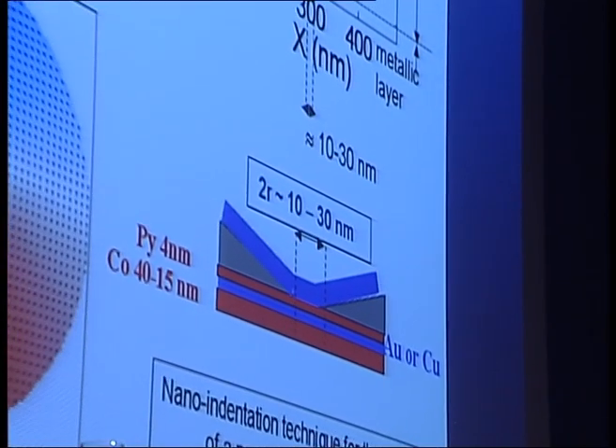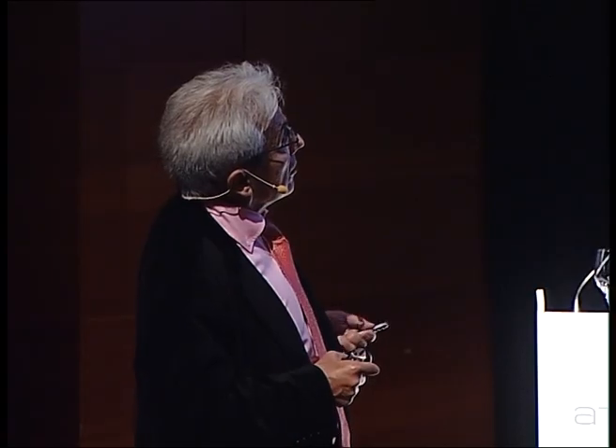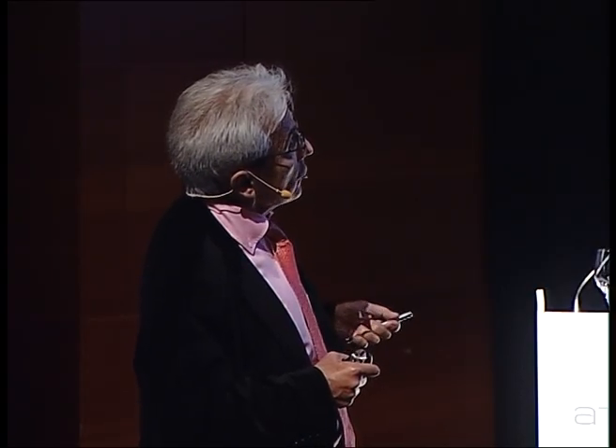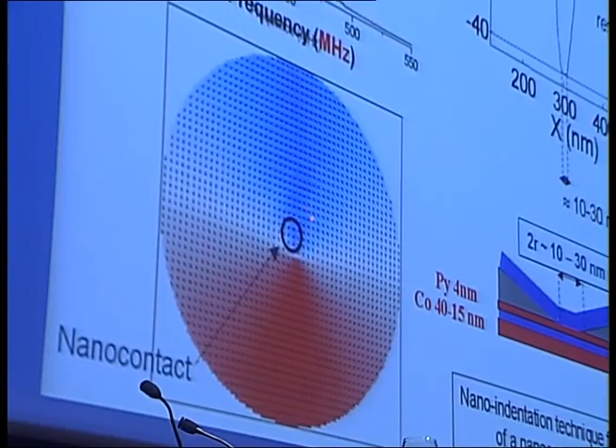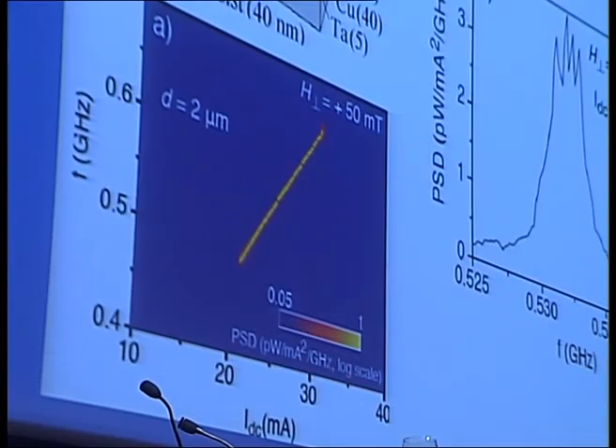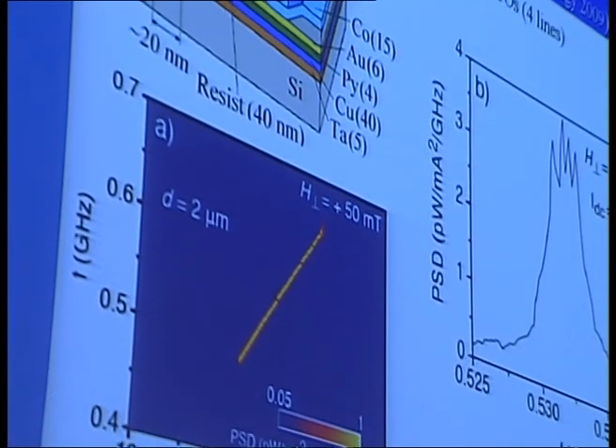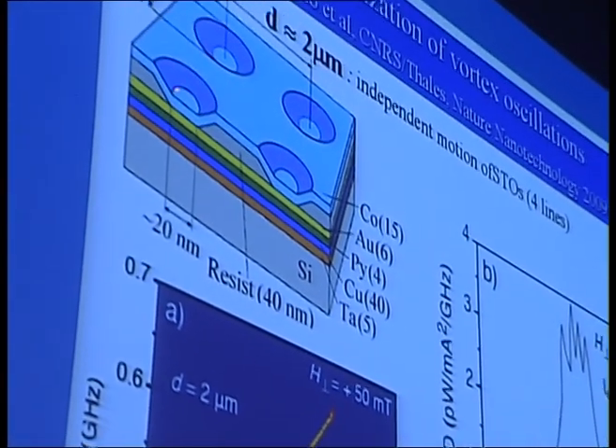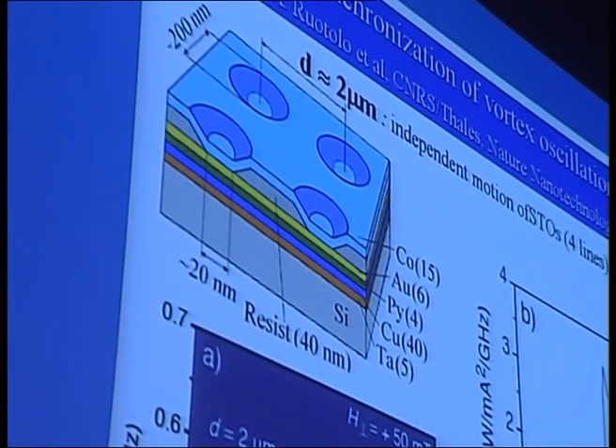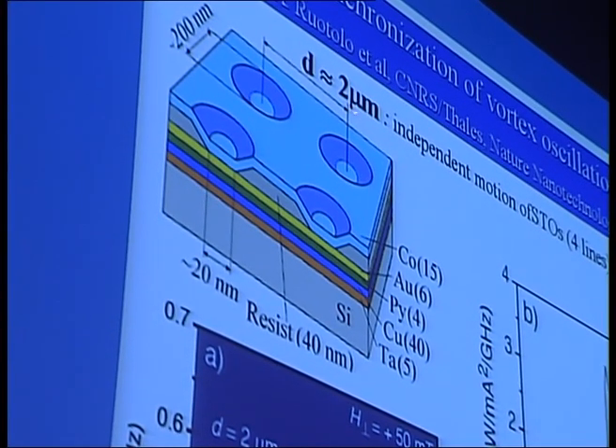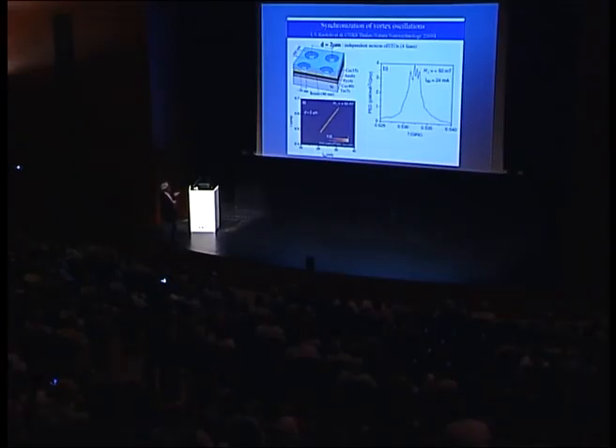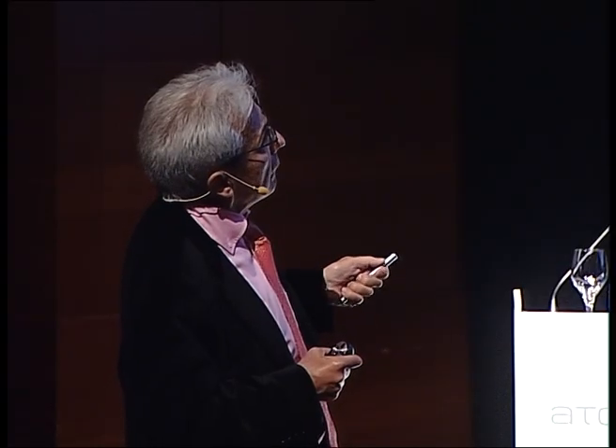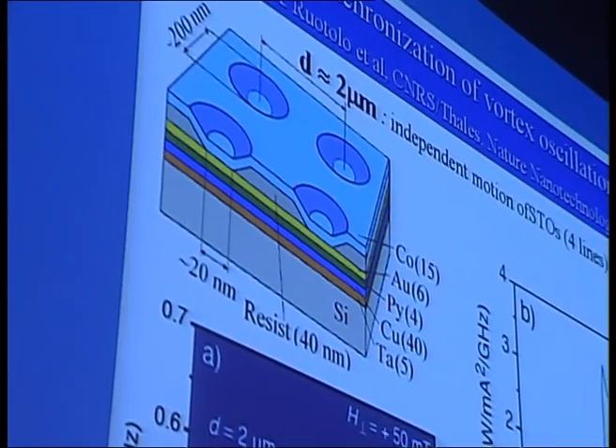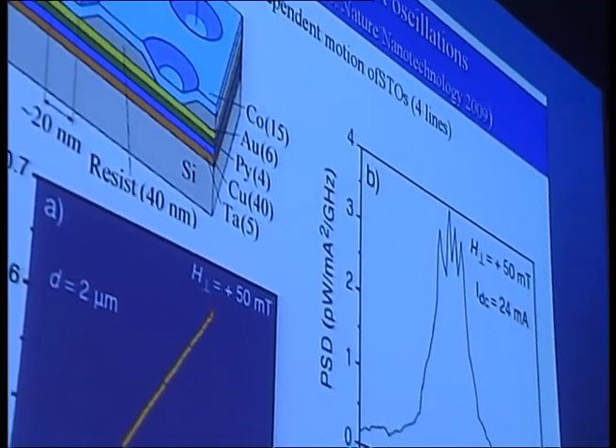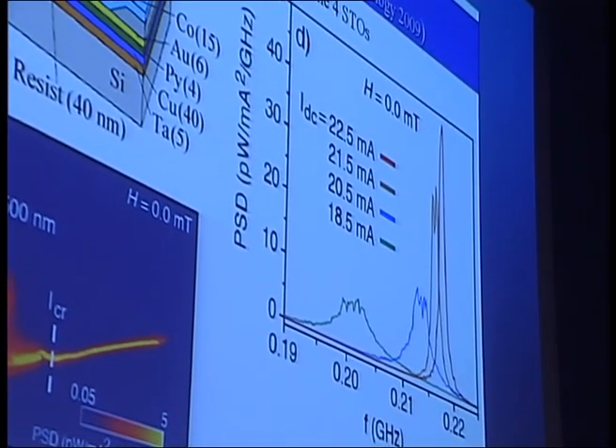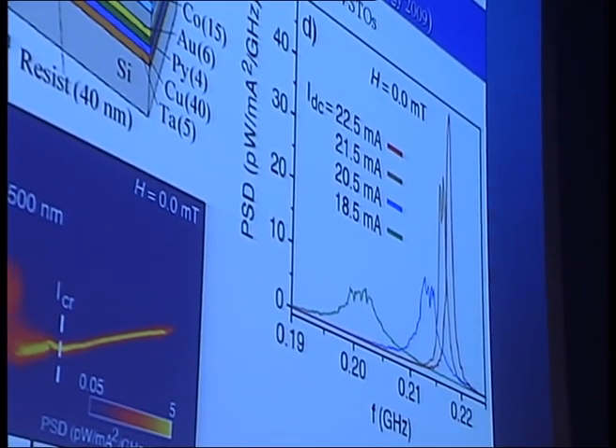And suppose with only one nanocontact, again, it is possible to generate a rotation of the core of the vortex due to the spin transfer effects. And then when we put on the same sample an array, for example, 4 nanocontacts to induce 4 vortices, when the distance is 2 microns, it's too long. There is not enough interaction between the vortices in different nanocontacts, and we see only 4 lines corresponding to the 4 nanocontacts. But by decreasing this distance to, say, half a micron, now there is a synchronization.